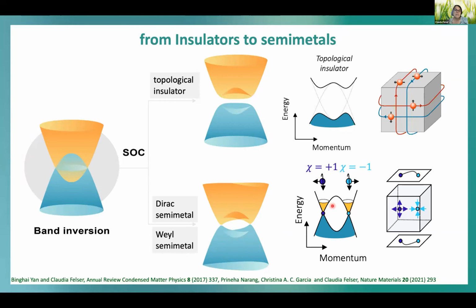And these Weyl semimetals are especially interesting because the degeneration points have chirality, so they are distinguished from a Dirac point. This is a doubly degenerated point. And since spin and momentum is locked, the electrons here are distinguished from there. And we have a Berry flux between these two kinds of reciprocal space momentum.